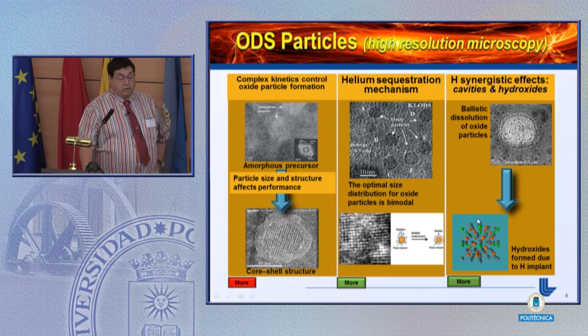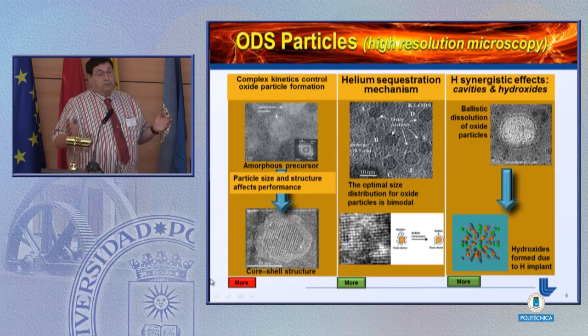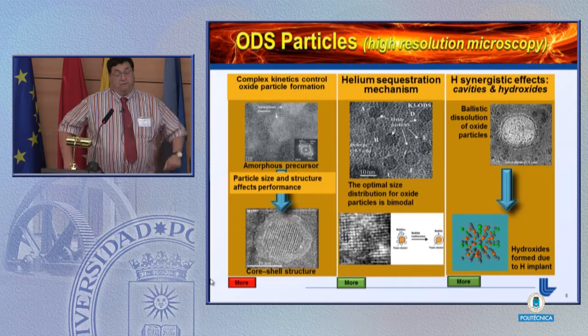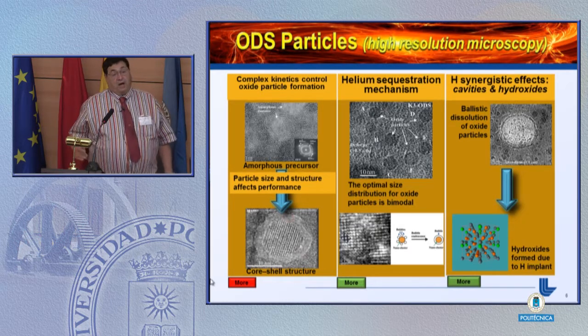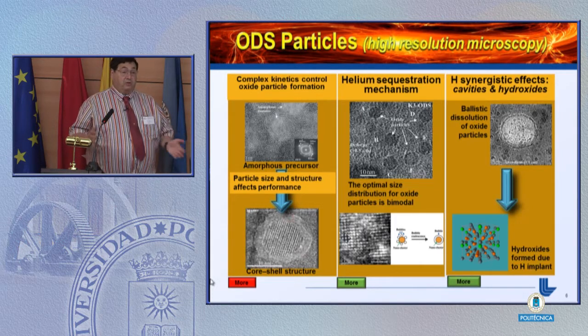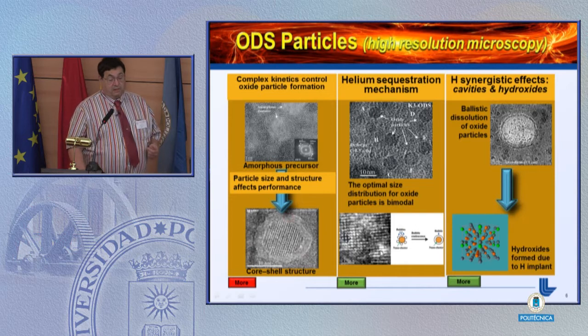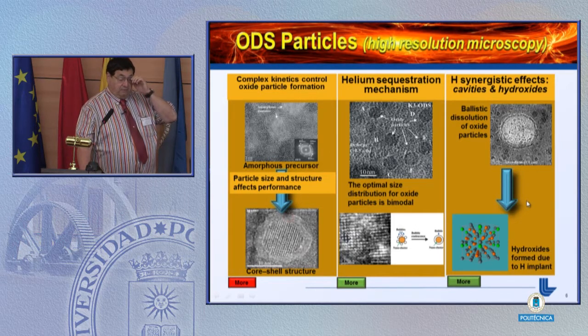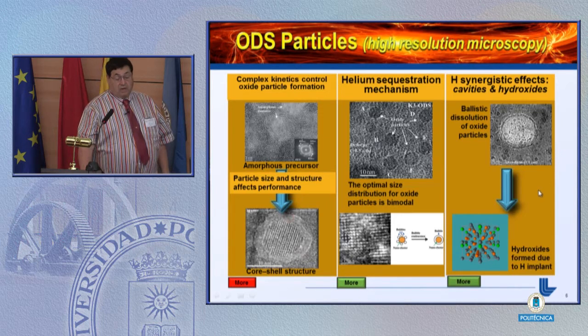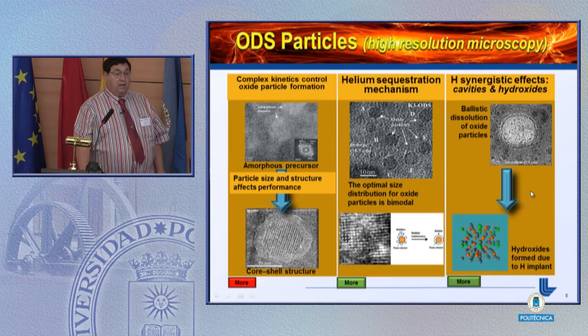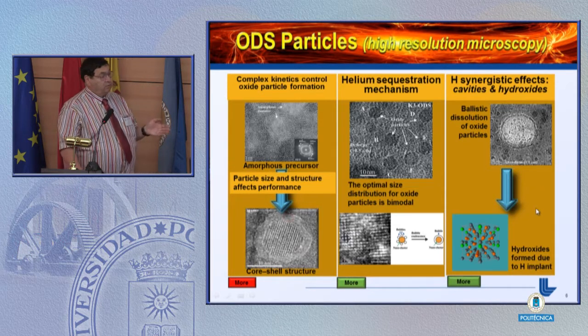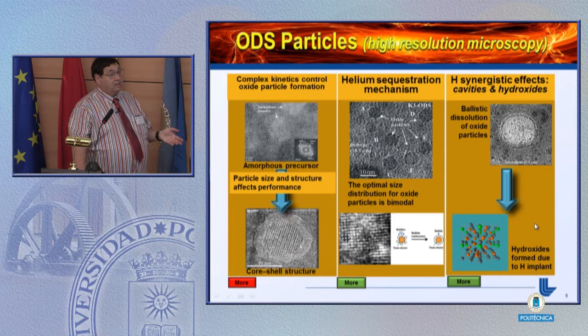Now, one thing that is really very, very different about the fusion environment when it comes to radiation damage compared to the fission environment is the large amount of hydrogen that's being produced relative to the helium. The large amount of helium that's being produced per dpa is also very different. But this hydrogen synergistic effect is something that started to bother me when I saw data from Japan, now almost 8 or 9 years ago, where they were irradiating F82H, which is another candidate RAFM, reduced activation ferritic martensitic steel, which is a candidate for fusion energy as well.